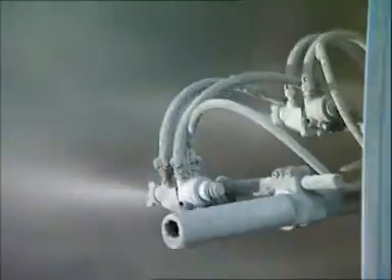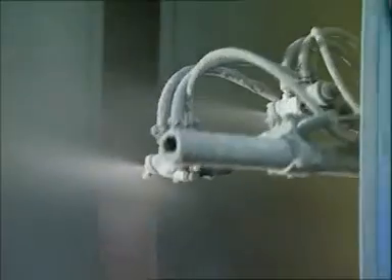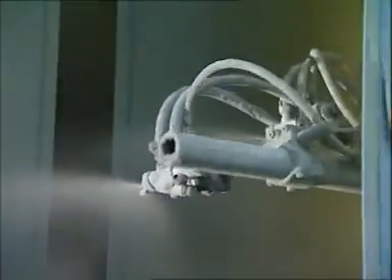The glass slip, which contains no organic solvents, is fed to the automatic guns applying the coating in a series of cabinets as the sheets travel through on the overhead conveyor system. The pre-coat provides a barrier against any residual hydrogen in the steel and enhances the adhesion of glass to steel. Additional coating regimes are applied to meet the specific requirement of the various agricultural and industrial finishes, all of which are environmentally friendly.